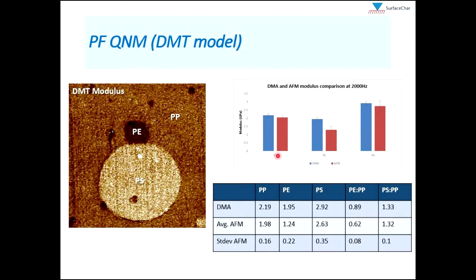So here's an example of an AFM method to measure these properties. PeakForce QNM, and it's using the DMT model, so adhesion just outside the contact, on this blend of polypropylene, polyethylene, polystyrene. And you can see we've compared the modulus measured by AFM, that's in red, with the DMA value and getting very nice accuracy with those.